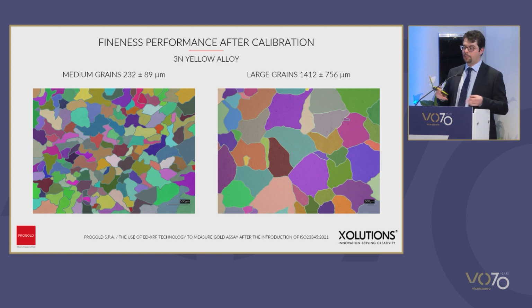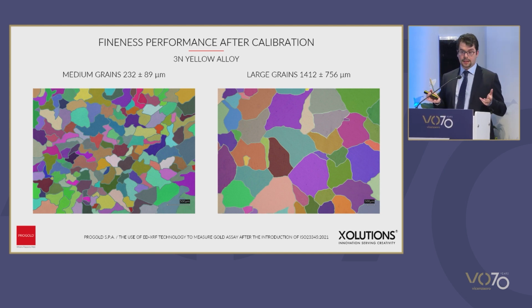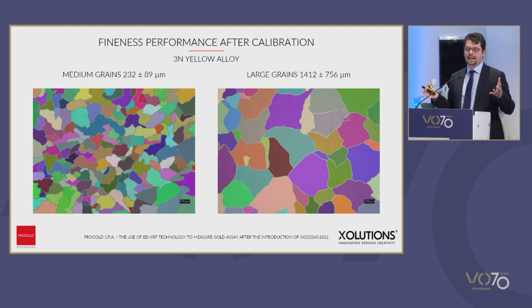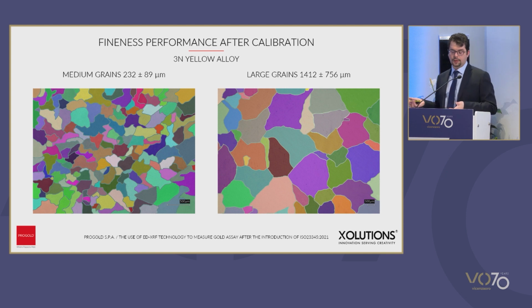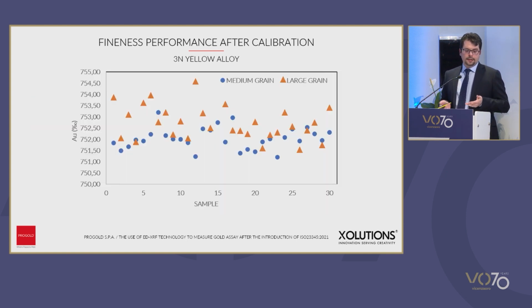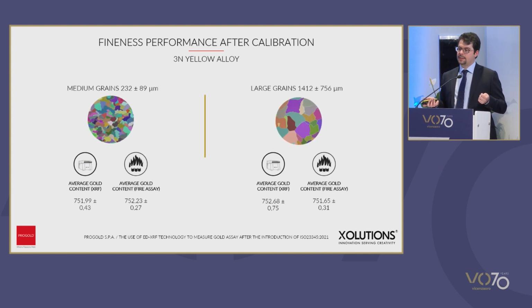Now, let's have a look at the results after making calibration, choosing these parameters on the three alloys that I mentioned earlier. Gold alloy, where we wanted to see whether there was a difference between the fine grain microstructure and the large grain microstructure. And these are the results that we achieved, and that are summarized in these two slides.